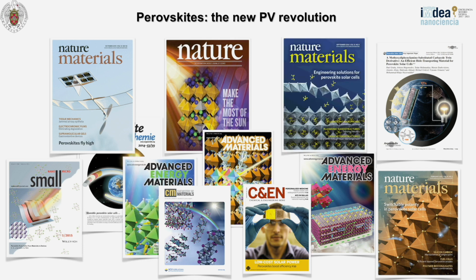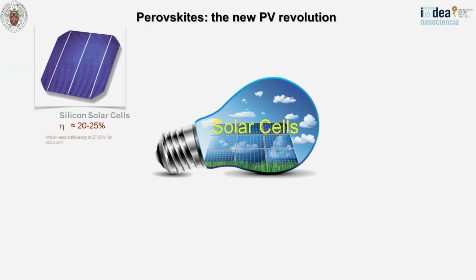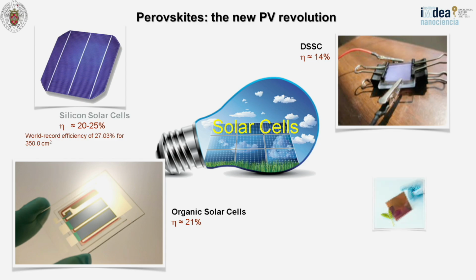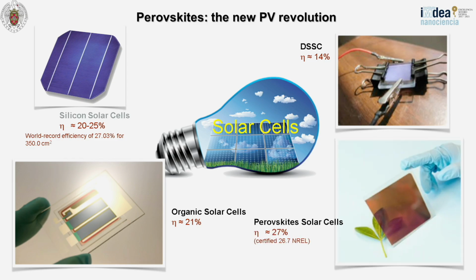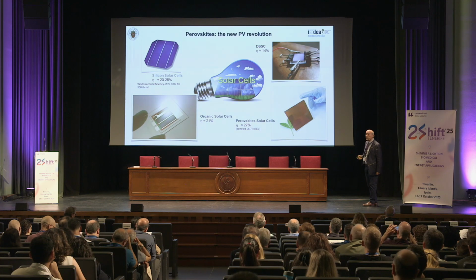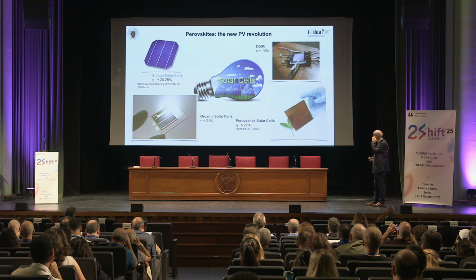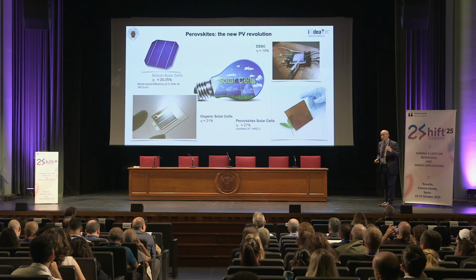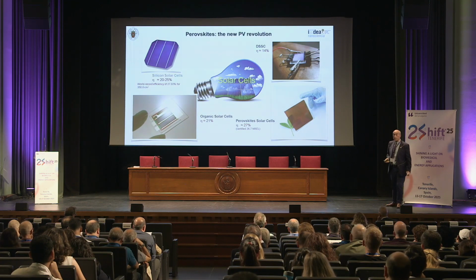Perovskites mean a revolution. This is clear because from the very beginning, it was considered by the scientific community in this way. Just to show you how is the state of the art in these systems. Silicon, this is the largest efficiency reported recently, around 27%, just for 350 square centimeters, which is really amazing. And also dye-sensitized solar cells is around 14%. Organic solar cells recently surpassed 20% efficiency. These are world records, okay?